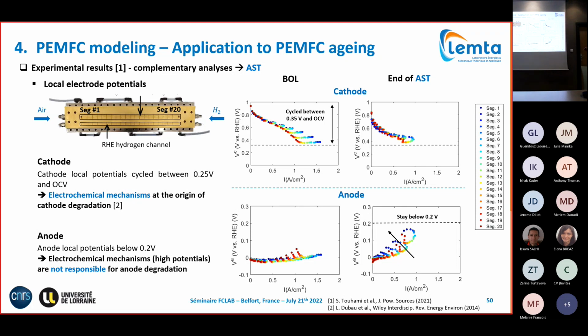Sorry, would it be reasonable to say your segmented cell corresponds to a stack? Because in a stack, you have the dimension of the cells, and then you have the dimension between cells. And it will depend if you have overflow or counterflow. So you have more considerations to take into account. You don't have the same distribution, so it's very complicated. But at least you can try to extrapolate it to different cells inside the stack, and even that with a lot of precautions.